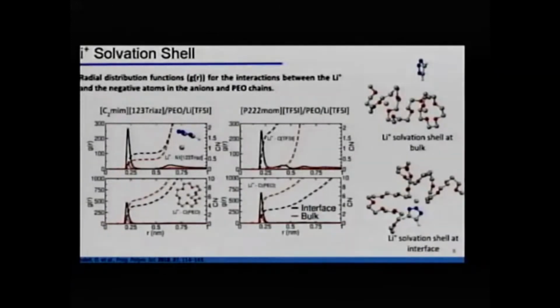anions around the lithium. And if we look at the RDF peaks, we see an increase in the intensity of these RDFs. So this means that this interaction is better structured in the interface than in the bulk. So we have a more ordered system close to the interface than in the bulk. But when we look at the interaction between lithium and the ether oxygens in PEO, we see a different behavior. Going from bulk to the interface, there is a decrease in the coordination numbers of PEO around lithium. That also agrees with our density distributions.